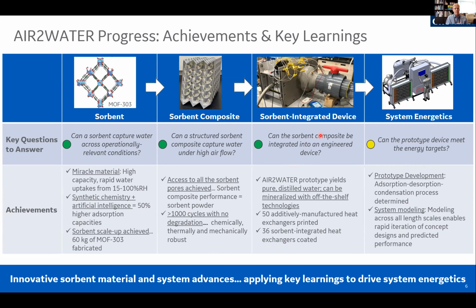Can we actually develop an engineered device? And absolutely we can, and we've done that. We can make pure distilled water the same way as Omar talked about in his passive system. And frankly, you're going to have to mineralize this to get the right taste for long-term consumption of that water. We've made about 50 of these additively manufactured heat exchangers. We've coated about 36 of them, and they all show this very high robustness, and then converted that into a system with a process that we've now determined: adsorption, desorption, and condensation.